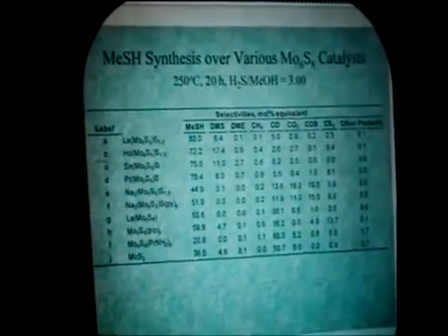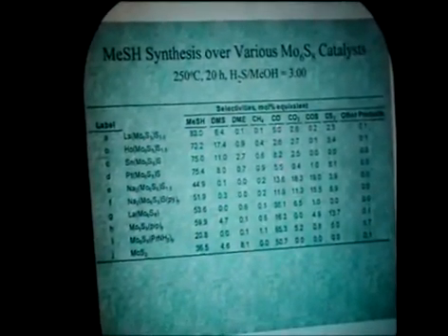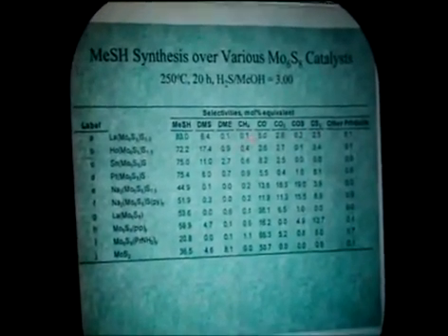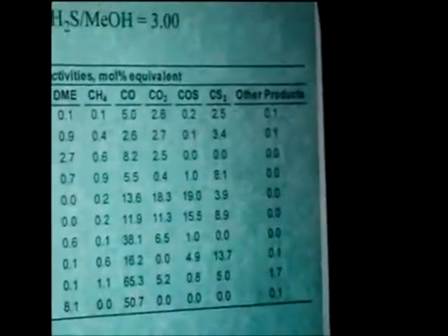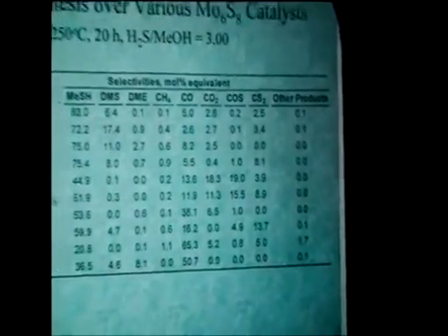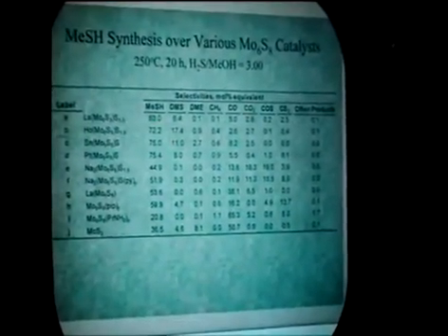The smaller ion types seem to have somewhat lower selectivities. Probably the other main thing to notice is that we have significant selectivities to these carbon oxides, CO2, COS, and CS2. So put it in the back of your mind: if there was a way that we could eliminate this type of chemistry, which really isn't observed in the commercial catalysts, these might be very selective catalysts indeed.